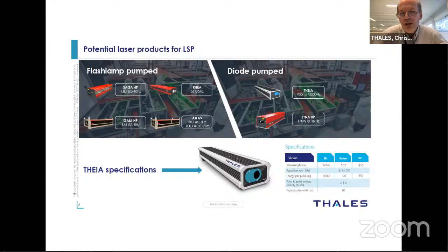And also in the diode pump laser, we can use essentially the THEIA, which is a laser delivering, as you have in the details below, up to 1 joule at 1064 and 700 millijoule in the green, at up to 200 Hertz. What is interesting in that solution is that this new laser, which is a relatively new product, is perfectly fitting with the findings I have shown in the slide before, because it's better to work with a small spot size, and you need much less energy per pulse.